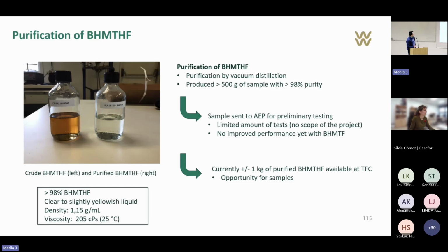So the 98% pure BHM-THF is a clear to slightly yellowish liquid. It's pretty viscous, with a viscosity of about 200 centipoise and a density of 1.15 grams per milliliter. The color is also quite stable, it doesn't change over time. This is available for anyone interested.